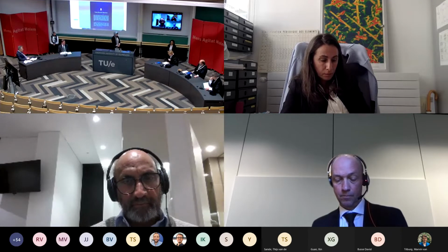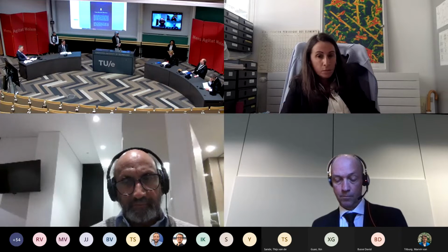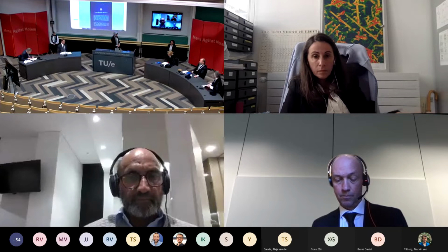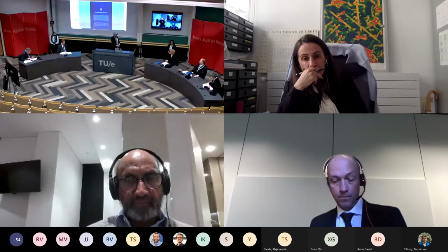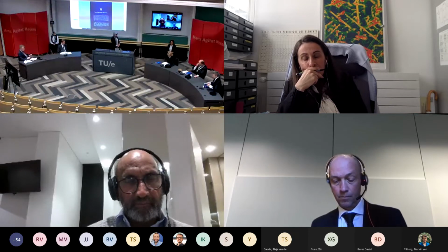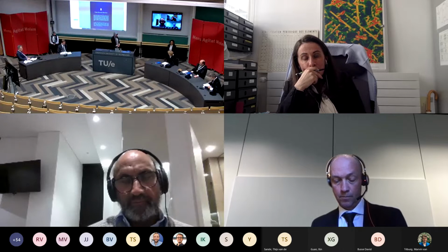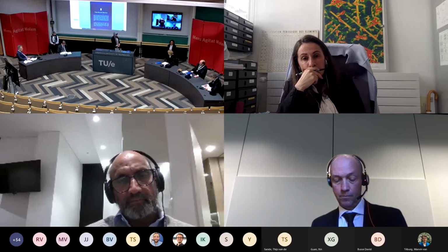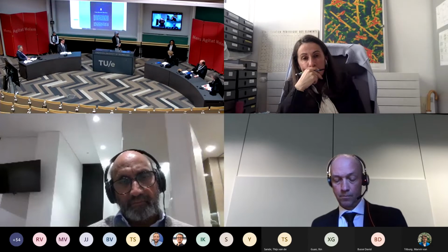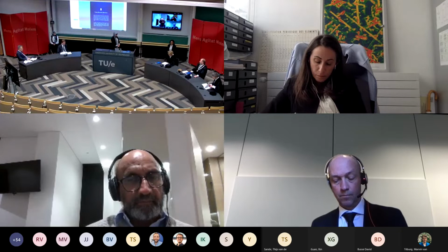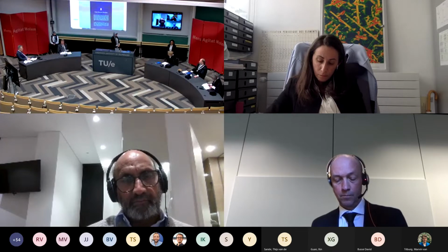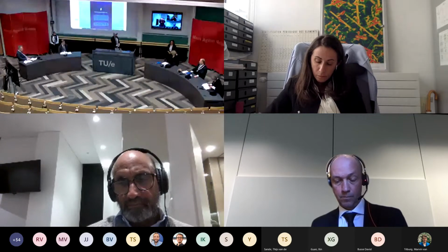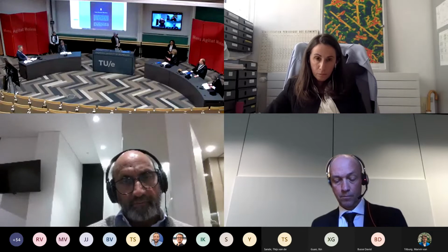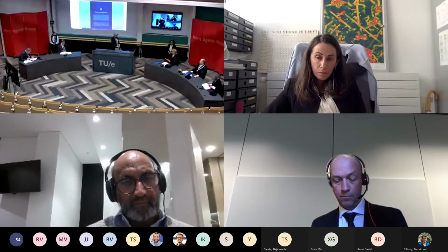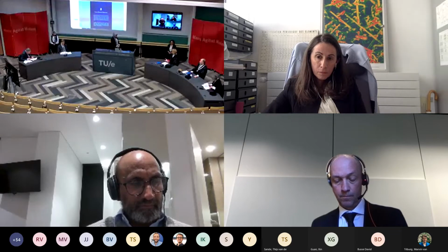Right. Okay. Thank you. Then I would like to talk to you about the incubation period that you see when you grow a hexagonal germanium. You see a two regime growth, basically. You have the incubation and then it starts growing. And then you found in the literature that this incubation is probably caused by the fact that the arsenic is getting out of the core at the interface, and therefore you can form a gallium germanium interface, which probably promotes the growth. But then I'm thinking, after you have formed the interface, then you start making germanium bonds, obviously. So you see a two regime growth, but shouldn't that be a three regime growth? So the incubation period where you evaporate a part of the core to make the surface ready for your growth, then the heteroepitaxy, and then the homoepitaxy.